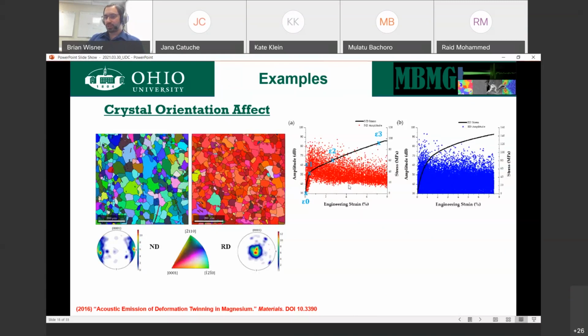We can then monitor this and not just look at the difference in mechanical behavior, but look at trends in non-destructive testing. So these dots that you see in both cases are acoustic emission trends. In both cases, we're seeing, generally speaking, that if you look at this, we have material here. We have energy in both cases that spike around yield, but there's a very different amount of activity going on. Why?